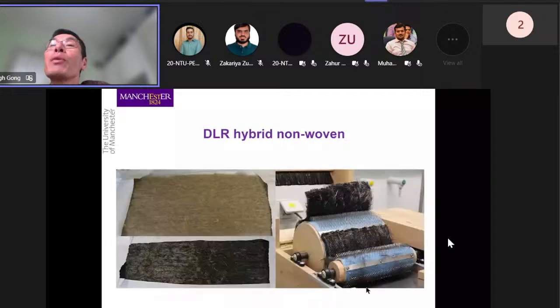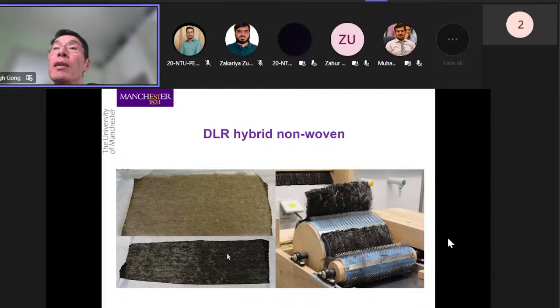And then you are successful in making graded non-wovens, graded in the sense that the mixing of the flax fiber and the carbon fiber can be different in the thickness direction of the non-woven. In other words, you can have a fully carbon fiber side, and then the other side is fully flax fiber. So this allows you to tailor the performance of the eventual composite depending on the application requirement. But obviously, this is done manually, so we needed something more mechanical.